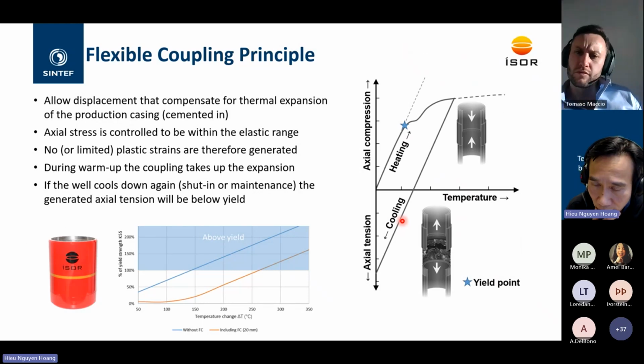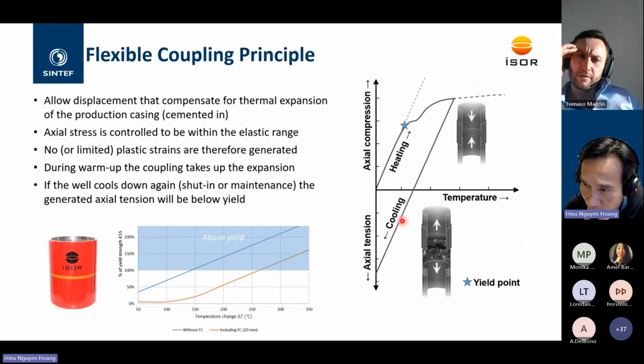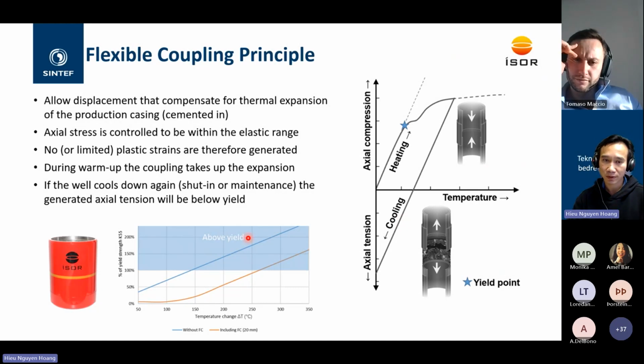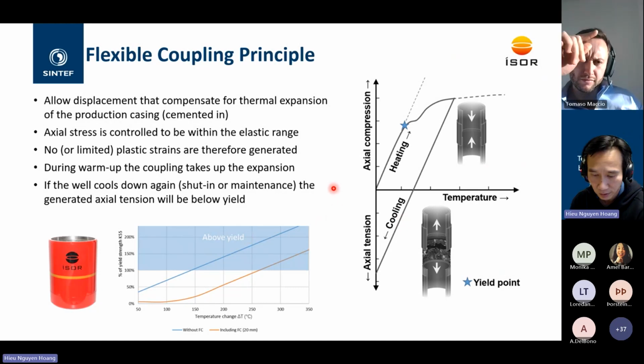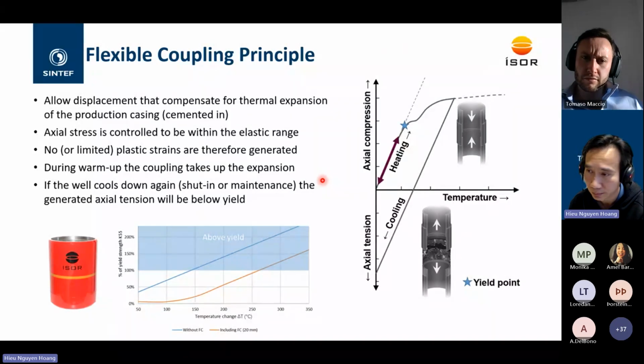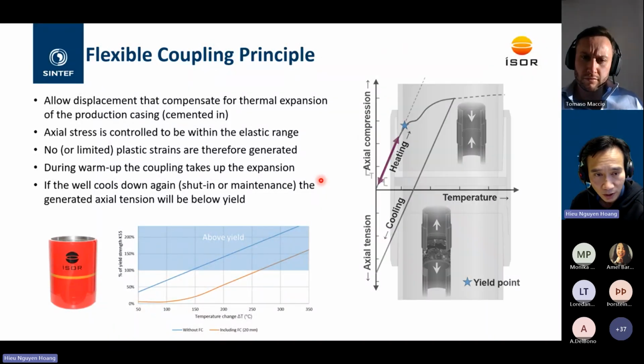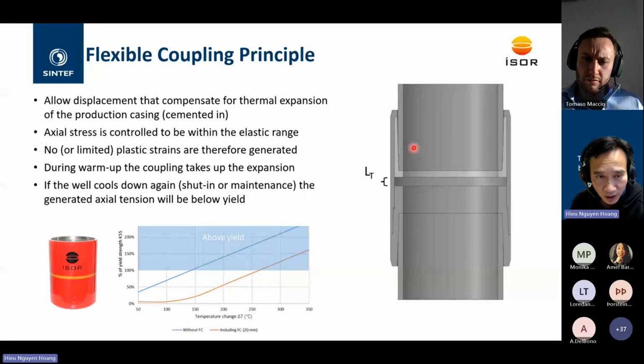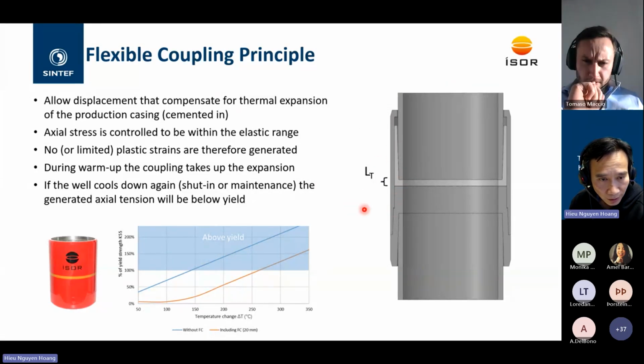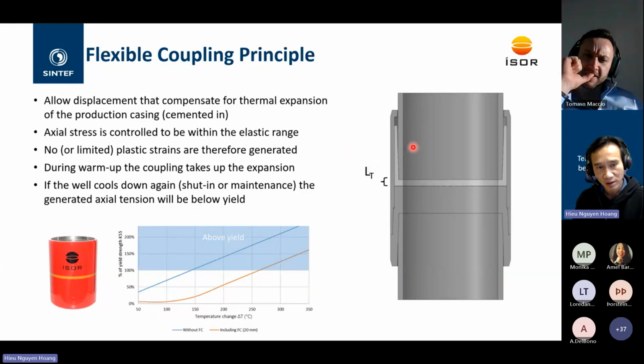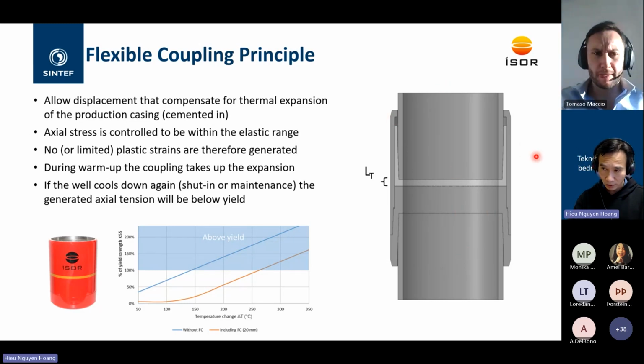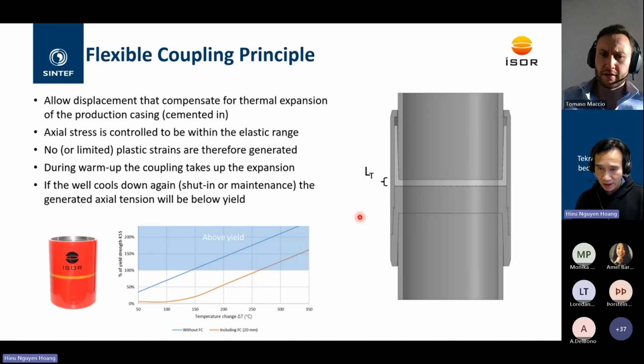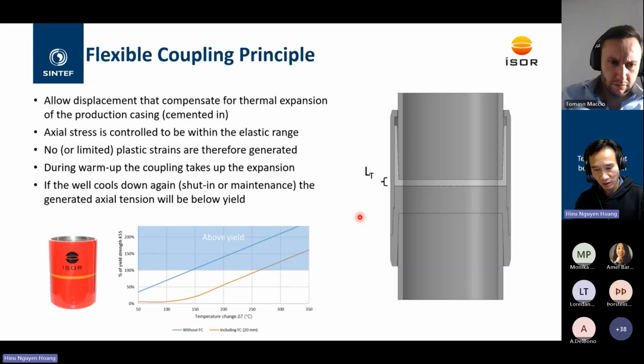And let's have a look at how this flexible coupling works. As you see here, when we are heating up the casing, the flexible coupling absorbs the thermal expansion, allowing the casing to move in the axial direction, and absorb the thermal expansion in this direction, meaning keeping the axial stress at an acceptable level and preventing plastic deformation in the casing system as a whole. And this ensures the casing system remains intact during temperature fluctuations, making it a very attractive solution for future applications.